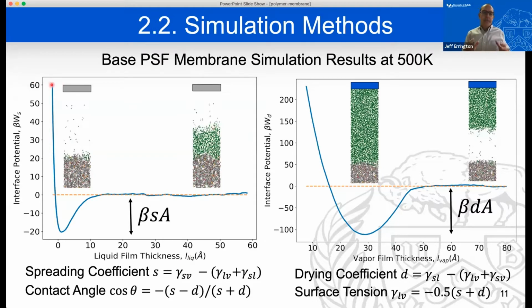So once you have one of these interface potentials, it can tell you qualitative and quantitative information about the wetting behavior. From a qualitative perspective, you'll notice here that this particular interface potential is one in which you have a minimum at relatively small film thicknesses, and that minimum then continues on to sort of this plateau region, which corresponds to the relatively thick fluid films. So if you have that type of situation in which you have this minimum that emerges, that tells you that the system is in the partial wetting regime. In other words, from a macroscopic perspective, the fluid would form a droplet on the surface.